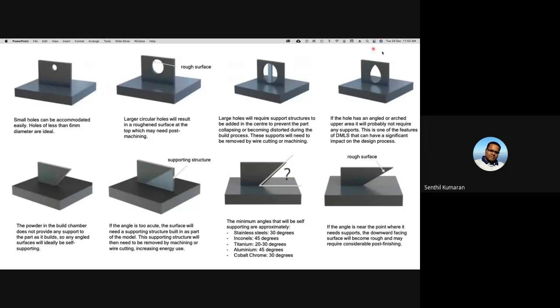So this is typically what the design guidelines or manufacturability guidelines are. Sometimes let's say you have a feature like this, a down-hanging surface. Probably you will have a support structure built like this, so you can actually have a very rough surface here. So you eliminate that. You can see, for example, stainless steel 30 degrees, Inconels 45 degrees, titanium 20 to 30 degrees, aluminum 45 degrees, cobalt chrome 30 degrees. These are the commercial materials, I would say, which are widely used. So you can minimize those. You can redesign in such a way that you have self-supporting surfaces.